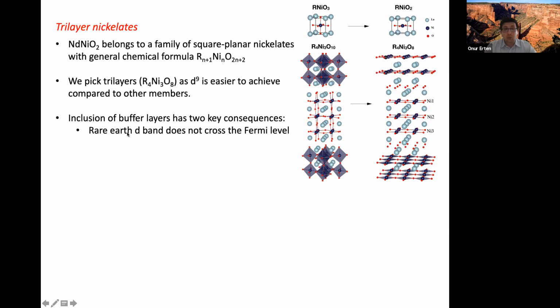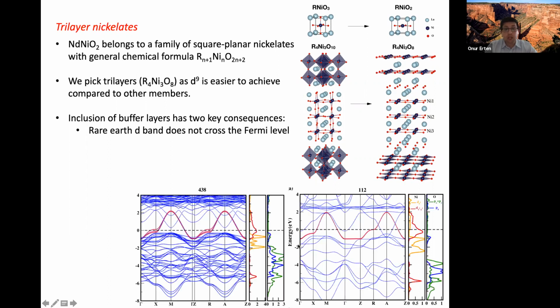And so this inclusion of these buffer layers, which leads to quasi two-dimensionality, is twofold. One is that because that rare earth band had mostly z-square dispersion, if you put buffer layers along the z direction, this reduces the hopping along the z, and therefore the rare earth band does not cross the Fermi level. This we can see in density functional theory calculations from my colleagues, where this is the infinite layer 112, where the superconductivity is observed. Here you have the rare earth band crossing the Fermi energy. Whereas in the tri-layer cases, this rare earth band is pushed to higher energies by mainly blocking layers to suppress the hopping along the z direction.